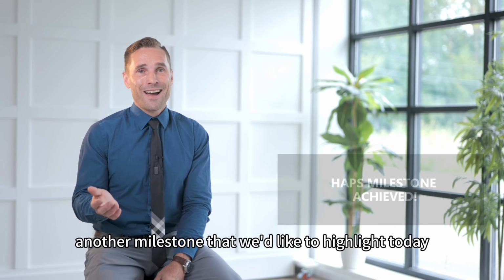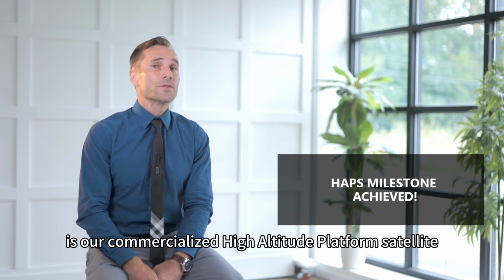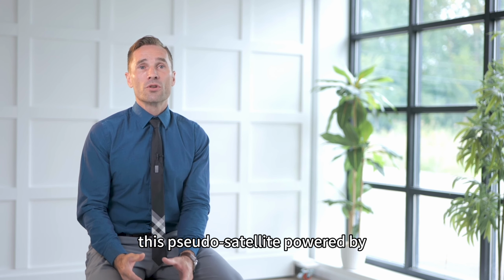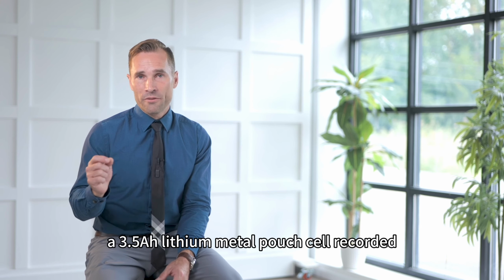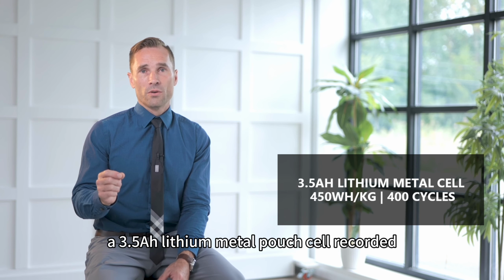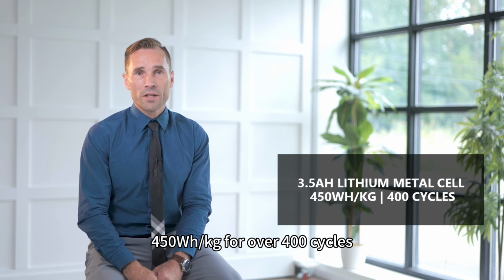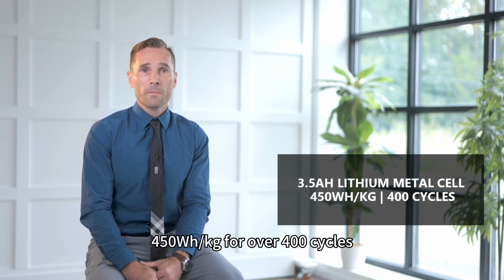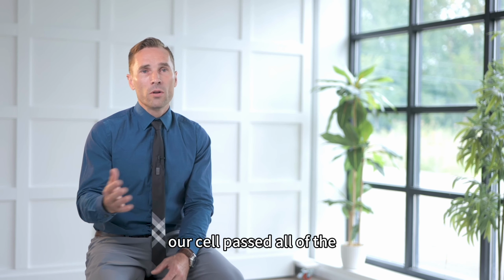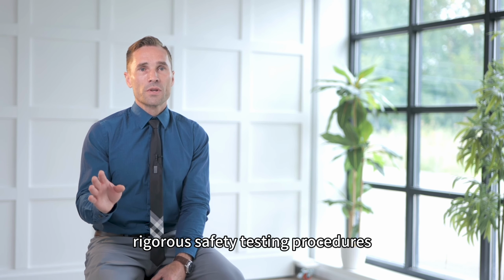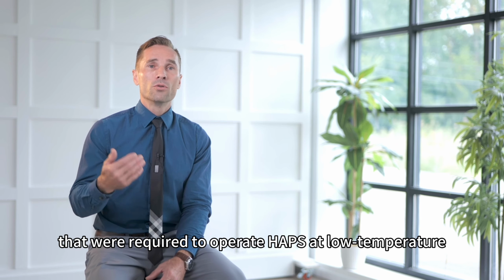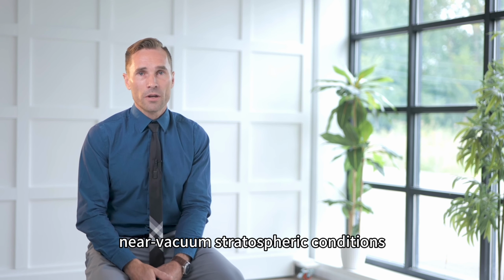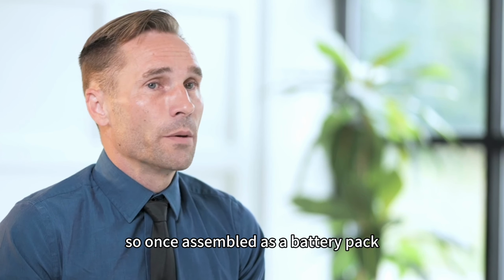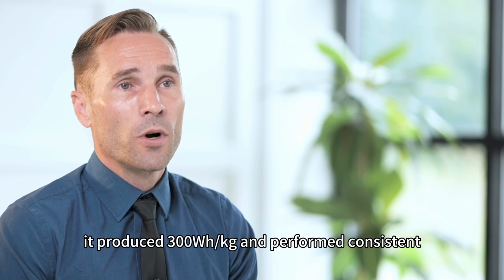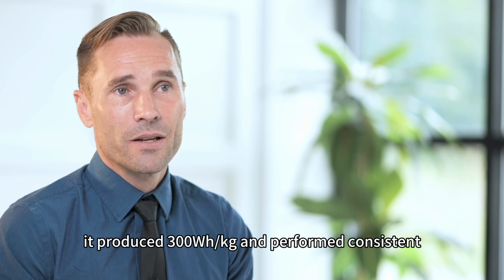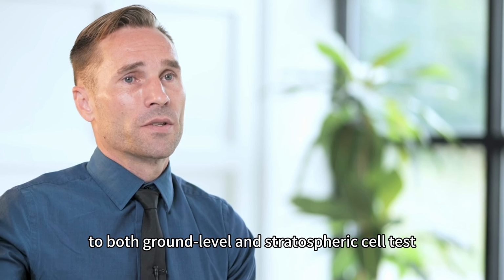Another milestone that we'd like to highlight today is our commercialized high-altitude platform satellite. This pseudo-satellite, powered by a 3.5 amp-hour lithium metal pouch cell, recorded 450 watts per kilogram for over 400 cycles. Our cell passed all of the rigorous safety testing procedures that were required to operate HAPS at low temperature near vacuum stratospheric conditions. Once assembled as a battery pack, it produced 300 watt-hours per kilogram and performed consistently in both ground level and stratospheric cell tests.